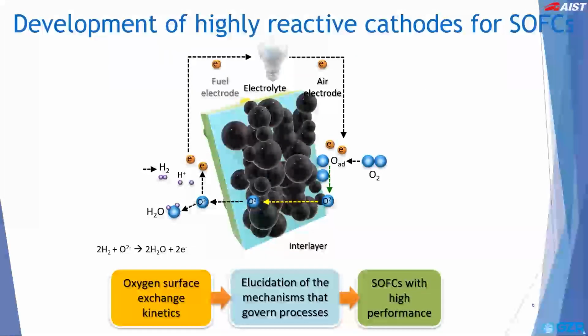One way to significantly improve SOFC performance is to increase the rate of oxygen exchange processes which occur on cathode materials. There are many types of cathode materials, but the most common ones are perovskite-type oxides, such as lanthanum strontium cobalt oxide or lanthanum strontium cobalt iron oxide. These materials have very high surface exchange properties, which enable the fast incorporation of oxygen from the supplied air into the cell.